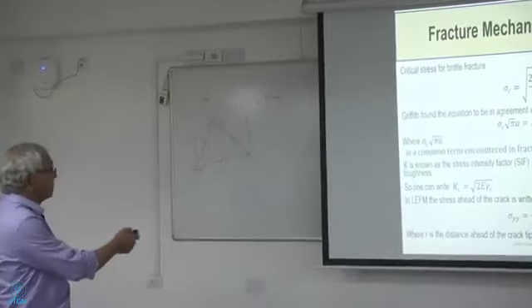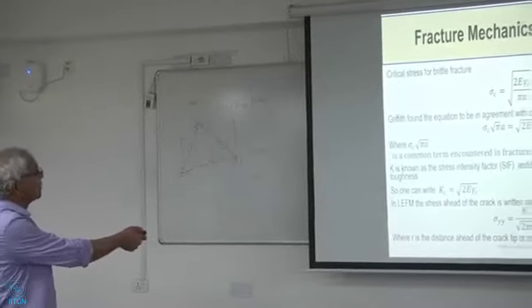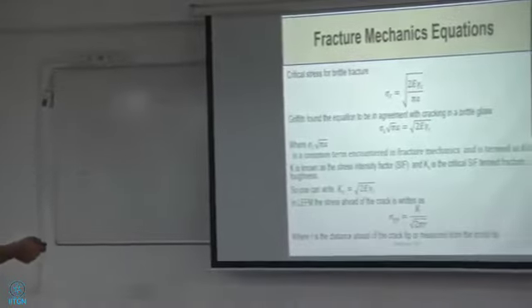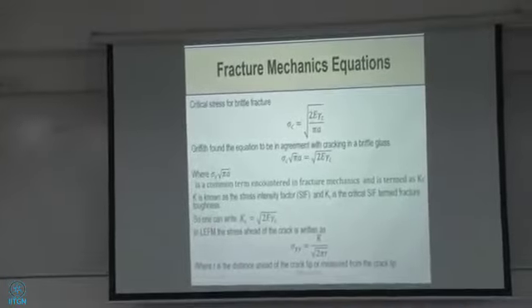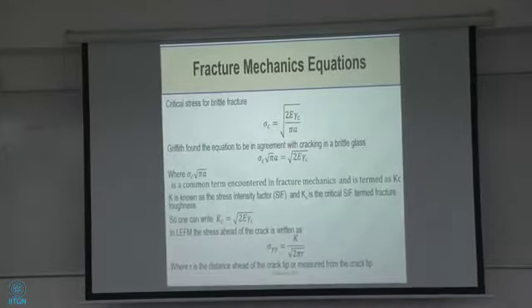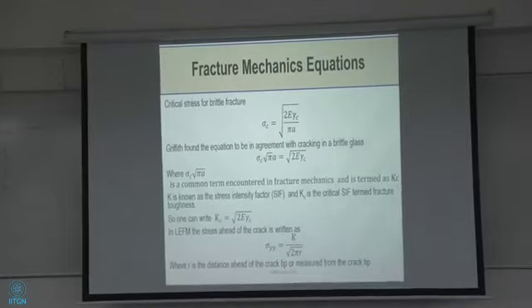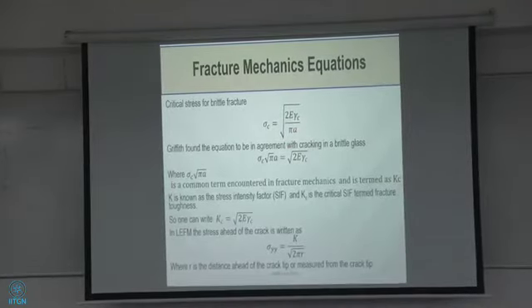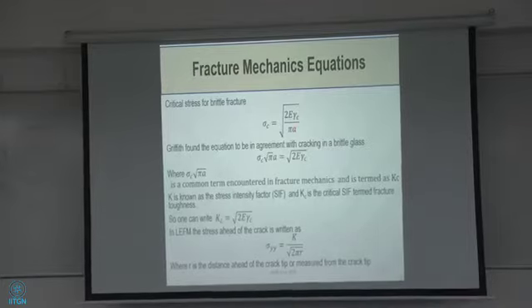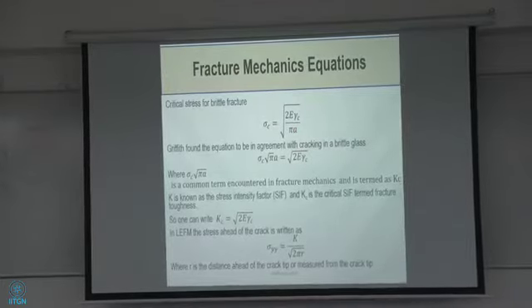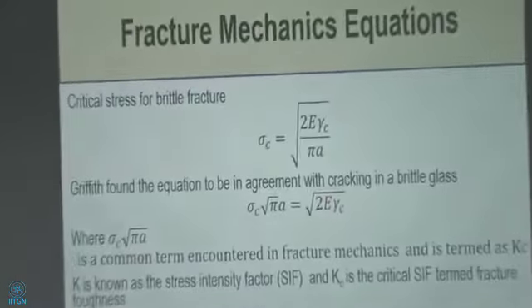So the critical stress for brittle fracture according to Griffith is this equation we just talked about. Okay? Found the equation to be in agreement with crack in a brittle glass. So you take the square root of pi a to the left side. Sigma sub c square root of pi a is equal to square root of 2E gamma c, right?